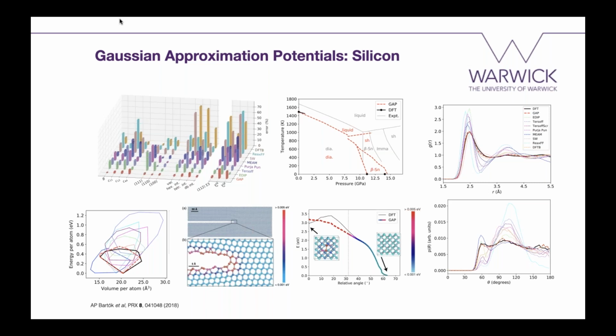And finally, and this is perhaps the most important test of all, is a random structure search on silicon, where we basically started geometry optimizations from completely random arrangements of atoms, and then relaxed these using different potential energy surfaces. So different colors are different models. Black is DFT, red is GAP, and all the rest are different interatomic potentials.